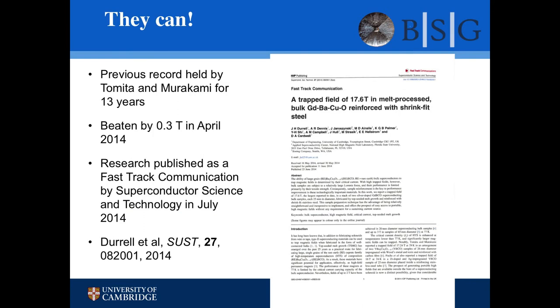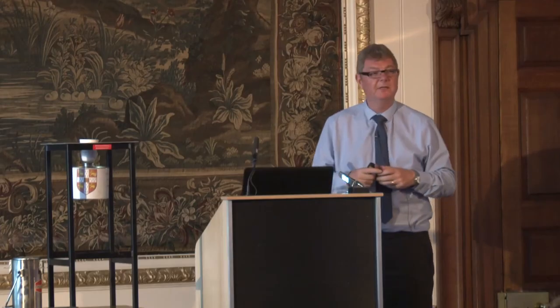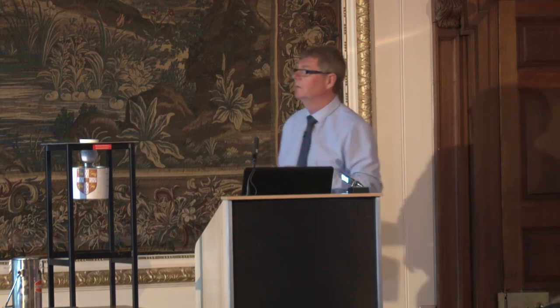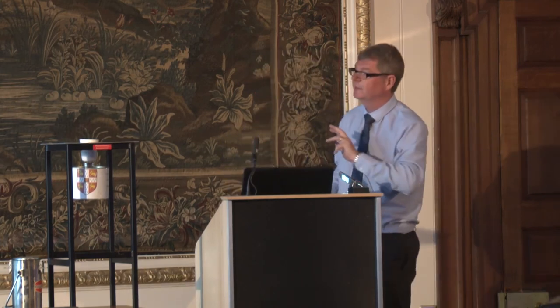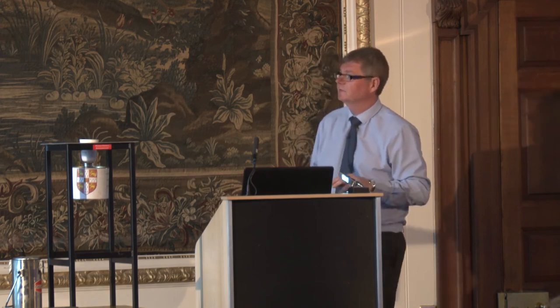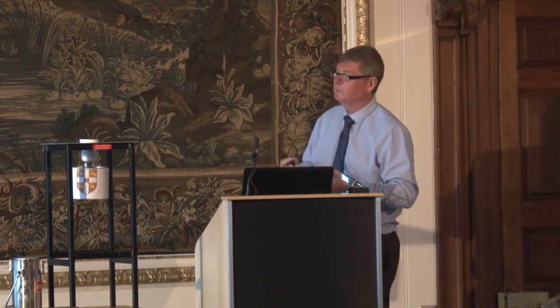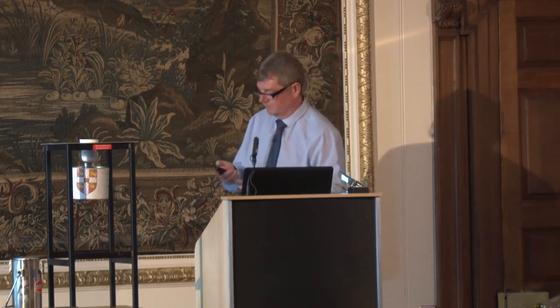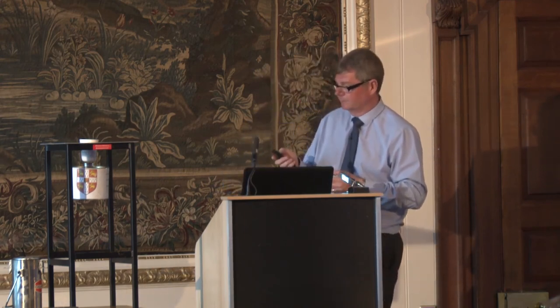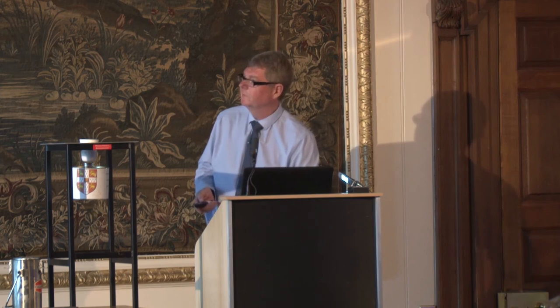So we produced this paper in July. The trapped field is 17.6 tesla, and so it beat the old record by 0.3 tesla in a gadolinium barium copper oxide sample. But the point about this is it's a standard sample. You just take a steel band, you heat the steel band, you drop it on your sample, and off you go. No specialist machining, no specialist reinforcement, no thermal management of the sample. So that was a new record.